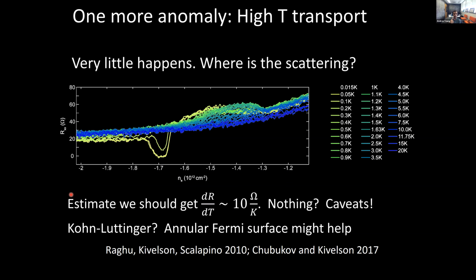if you have scattering off of a particular bosonic mode, let's say a phonon or some kind of appropriate magnetic excitation, the same things that might lead to some attractive pairing at low temperatures typically give you some scattering in the normal state. So, if you look at aluminum, aluminum of course has electron-phonon scattering at high temperatures, and actually the dimensionless electron-phonon coupling you extract from that high temperature behavior is the same as the electron-phonon coupling that shows up in the BCS formula to within 20 or 30%. It's not very different. Here we don't see much, which is sort of surprising.